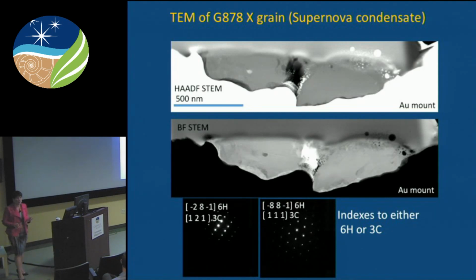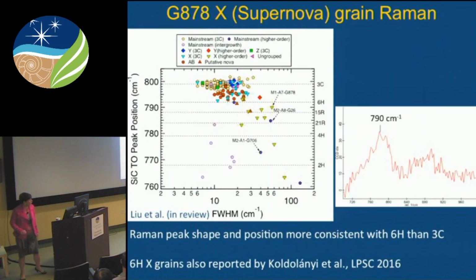When I take the electron diffraction patterns from different zones, I obtained patterns that were nearly equally well indexed to the 6H or the 3C cubic forms. Additional zone axes may allow me to differentiate, but it's not always possible. In this case, it wasn't possible to get to an additional zone axis to distinguish. So in this case, we go back to the Raman.